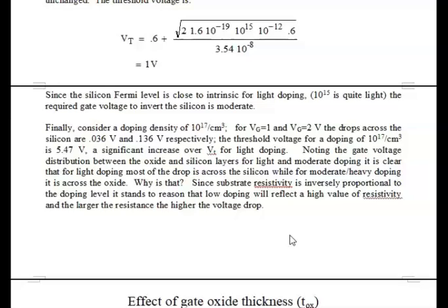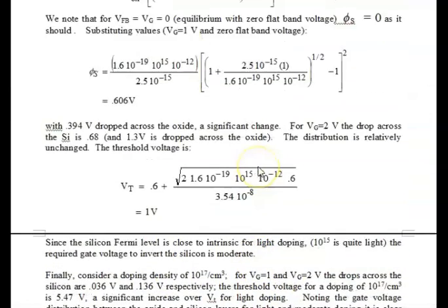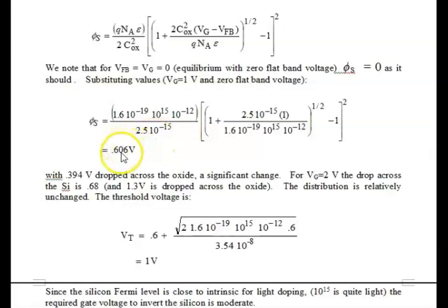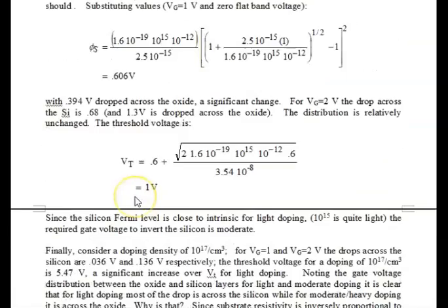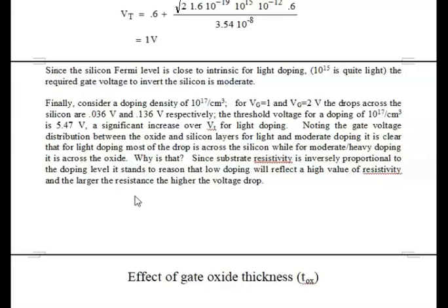So finally, we consider a heavy doping of 10 to the 17th. And we put in the same numbers, gate voltage of 1 volt, gate voltage of 2 volts. Again, the gate oxide is quite thick, at 1,000 angstroms. But we notice something rather interesting here for the heavy doping. Look at the drops across the silicon, the phi sub s: 0.036 for 1 volt and 0.136 volts for 2 volts. Especially for the 1 volt, it is minuscule compared to the 0.6. So we're dropping much less voltage across the silicon for the heavy doping than we do for the light doping. And why should that be?